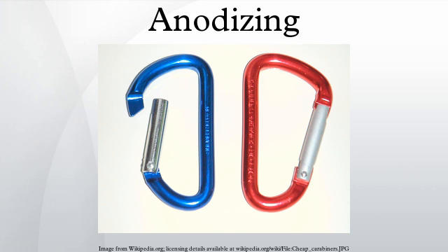Organic acid anodizing. Anodizing can produce yellowish integral colors without dyes if it is carried out in weak acids with high voltages, high current densities, and strong refrigeration. Shades of color are restricted to a range which includes pale yellow, gold, deep bronze, brown, gray, and black. Some advanced variations can produce a white coating with 80% reflectivity.